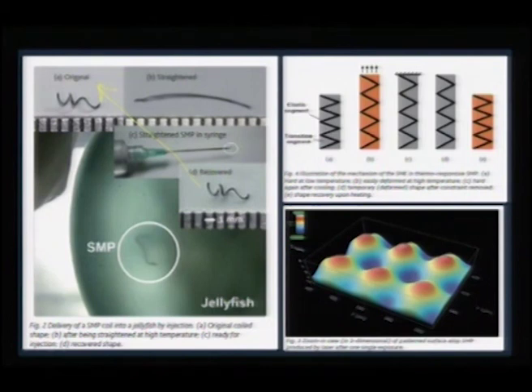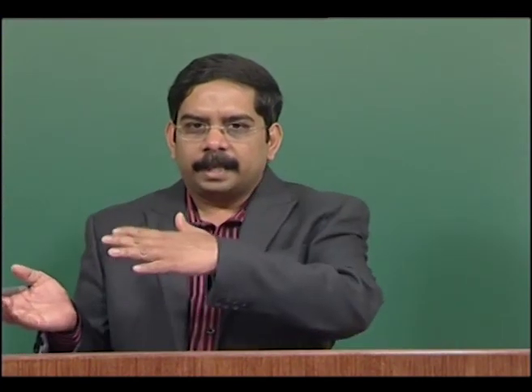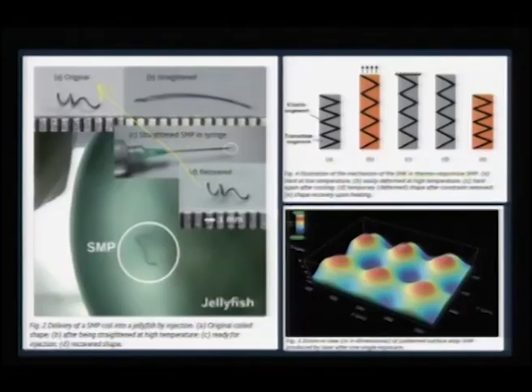And what is the mechanism? Unlike the case of alloys, where at high temperature they may be hard and at low temperature soft, in case of thermo responsive polymers, you have both the transition segment and elastic segment available both in the cold phase as well as in the high temperature phase. So this is exactly the opposite phenomenon of shape memory alloys, because in austenite it may be hard, in martensite it may be softer in case of shape memory alloys, but in this case both the phases are present either in the cold phase or in the hot phase.